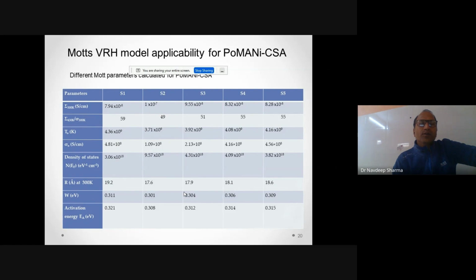So in the case of our conducting polymer, poly-orthomethyl aniline, we found that there are different parameters obtained from the Mott VRH model applicability. The conductivity was found to be better in sample 2, that is 1 into 10⁻⁷ Siemens per centimeter, and you have seen that the variable hopping distance is 17.6. It means that the hopping distance for the charge carrier is found to be less, and the energy density of states obtained in this ratio, S2, is maximum as compared to other samples.